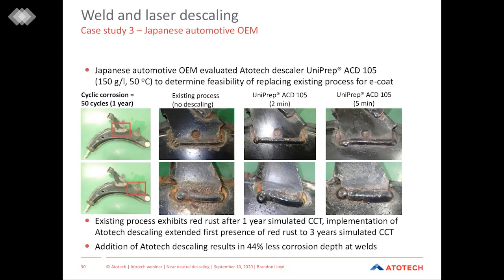You can see here on this part, the area of evaluation is right here along the welded area. As we move to the left, we can see with the existing process and no descaling that we start to see some significant rust along the welded areas right in here. As we move further to the right with the implementation of Uniprep ACD at 2 minutes application, we can start to see some reduction in the amount of rust that is exhibited along the welded area.